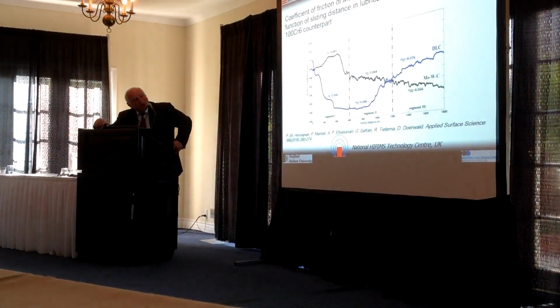specimens. What was the big difference between the behavior of these coatings and the standard DLCs was their friction behavior with time. The standard DLC was having initially very low friction coefficient, but with time it started increasing because at these high temperatures you start getting graphitization and the friction behavior deteriorates, whereas with the molybdenum tungsten doped carbon films, the friction behavior is completely different.